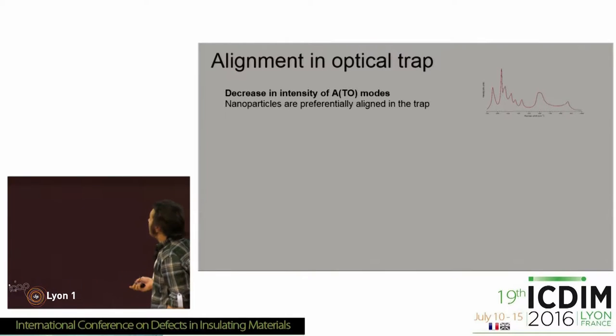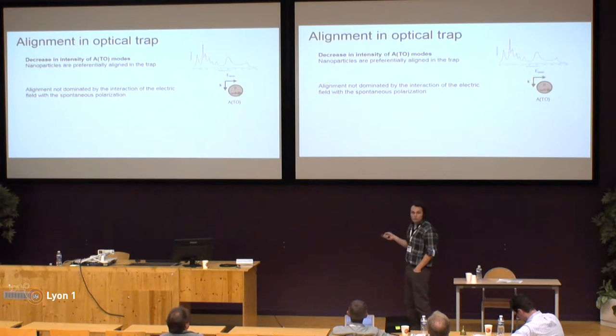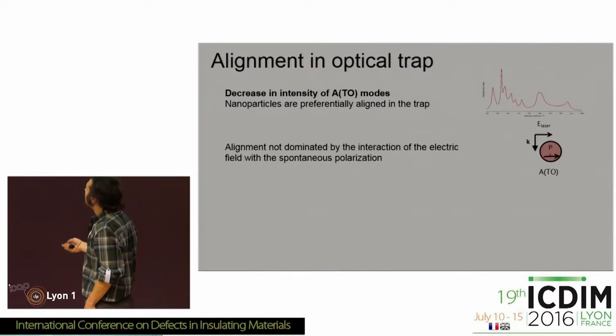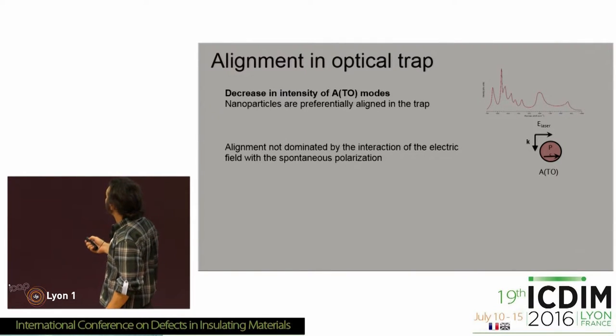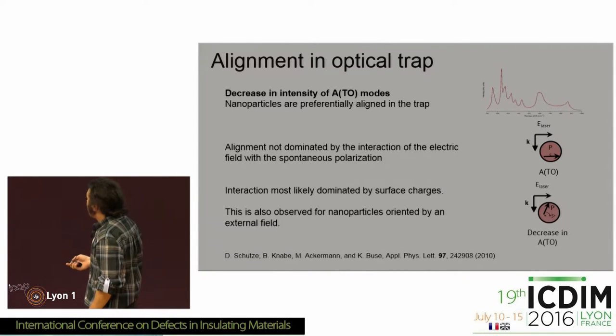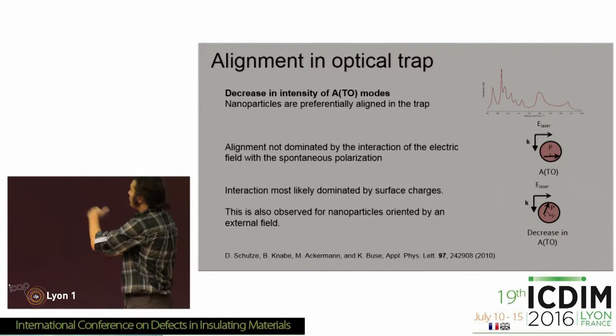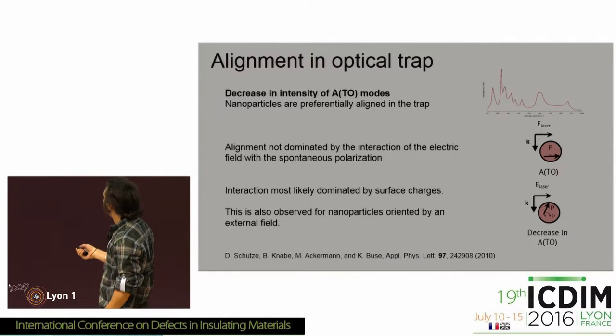Using the mode assignment from the literature, despite that distribution in orientations, you can somewhat get an idea of the preferential alignment of the nanocrystals. You might think the spontaneous polarization would align parallel to the polarization of the electric field of the incoming light. If that were the case, you would see the ATO modes in the Raman spectra, but that's not the case — when you do the mode assignment, you see a lot of ETO modes, and the ATO modes are suppressed.